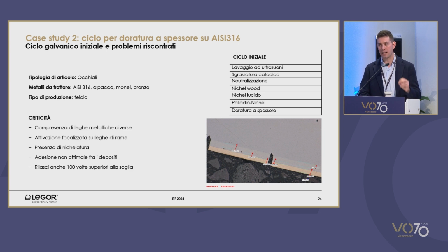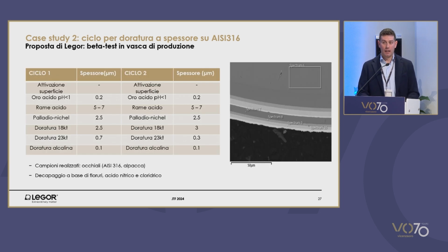Such cracks, therefore, can lead to the migration of nickel from the object to the wearer. The nickel included both in the stainless steel alloy and the releases in this case were unacceptable. Legor has come up with a proposal including 2 different cycles. These cycles have been developed in the manufacturing process.